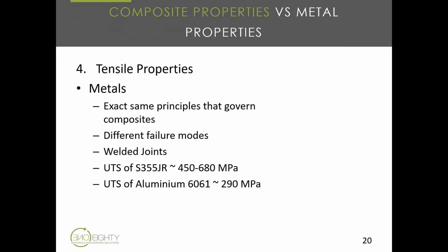So, tensile properties. For metals and for composites, they're exactly the same. It's the same type of test, just different shape material or sample, which we'll go into. But you're able to determine, for both metals and composites, the different failure modes of the material. For metals, the tensile test is typically done for welded joints, especially in the marine industry, to see if the weld is strong enough for its application.